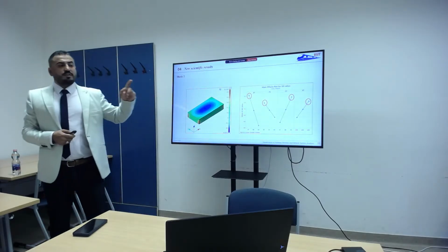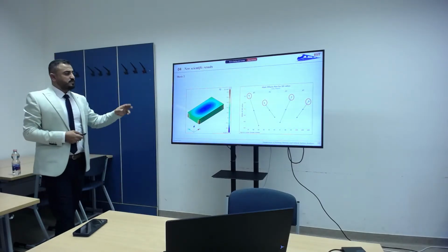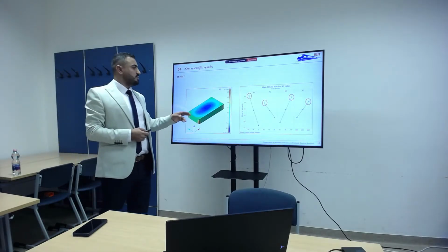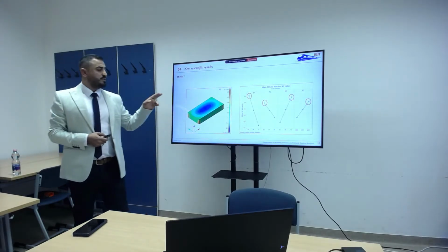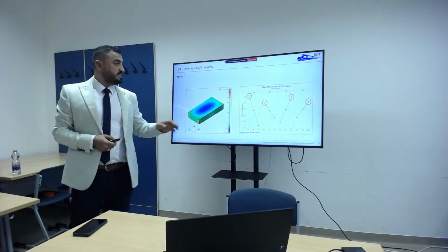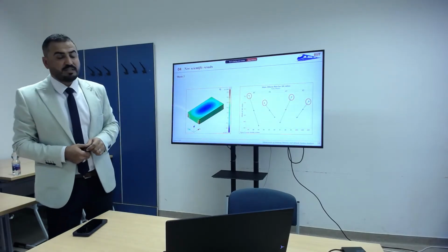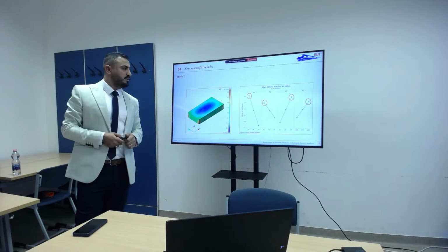Also, I found the optimal levels of each parameter. For the bed temperature, it was 87 degrees Celsius. For the printing speed, 30 millimeters per second. For the chamber temperature, 37 degrees Celsius, and for the printing temperature, 235 degrees Celsius.